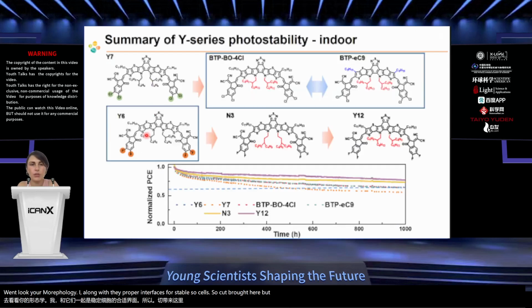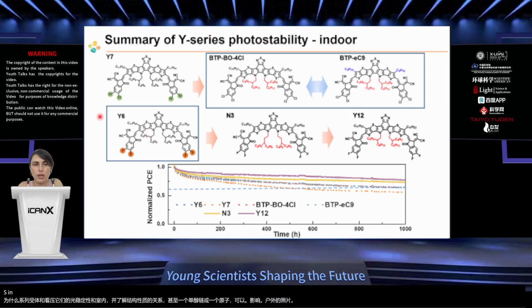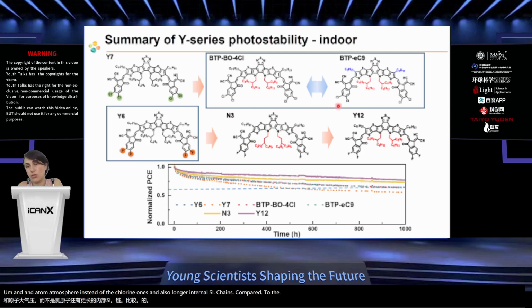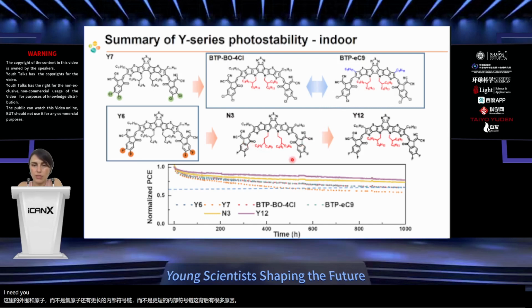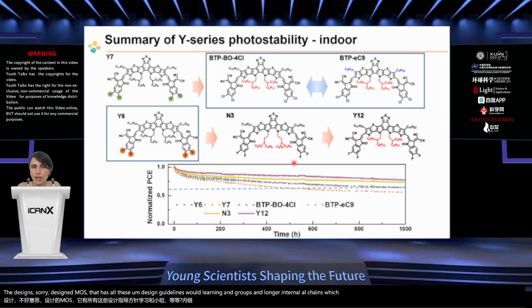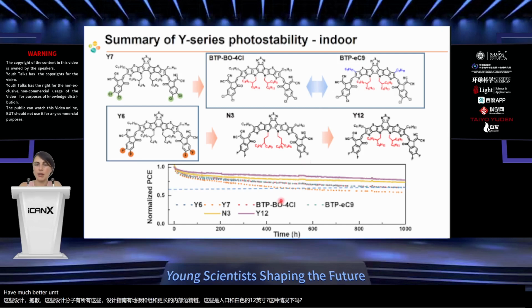I'll cut it short here, but we looked into a wide range of Y series acceptors and looked first at their photostability indoors, to understand the structure-property relationships, how even a single alkyl chain or an atom can impact the outdoor photostability in the future. Among these, we came up with a design guideline that we need to choose fluorine-type peripheral end atoms instead of the chlorine ones, and also longer internal side chains compared to the shorter internal side chains, for which there are lots of reasons behind. If you do this and make devices, you see that the designed molecules that have all these design guidelines, with fluorinated end groups and longer internal alkyl chains, which are N3 and Y12 in this case, have much better stability compared to the other materials.